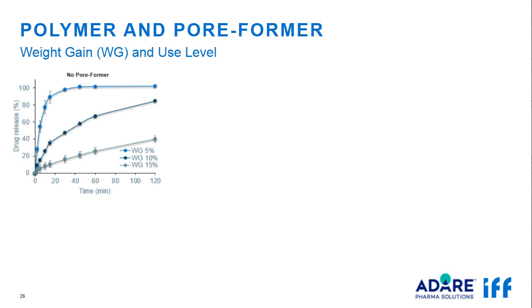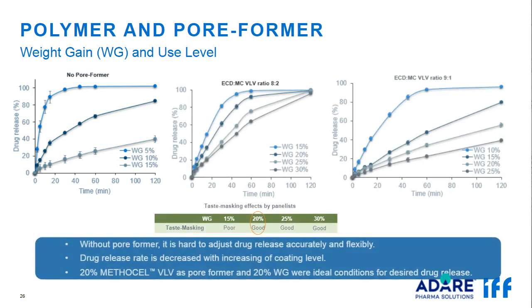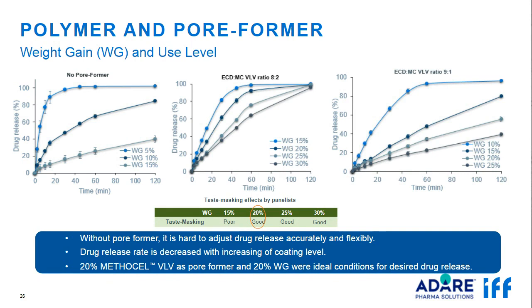The permeability of ethylcellulose film can be increased by incorporating a pore-former, as mentioned. We can adjust the drug release by coating weight gain and pore-former levels. These two dissolution profiles in the center and on the right show the impact of pore-former and coating weight gain on drug release. Methocel VLV was evaluated at 20 and 10% with respect to the polymer as pore-former. It was found that the 20% pore-former level with 20% weight gain hit the target delayed release profile while providing a complete drug release.